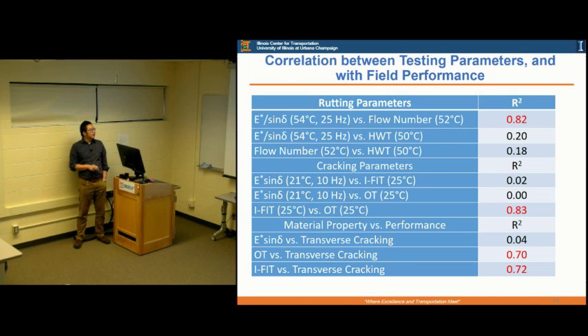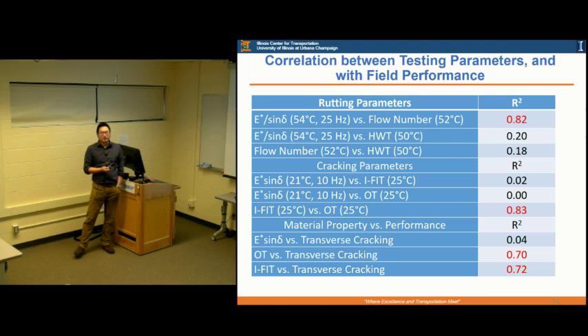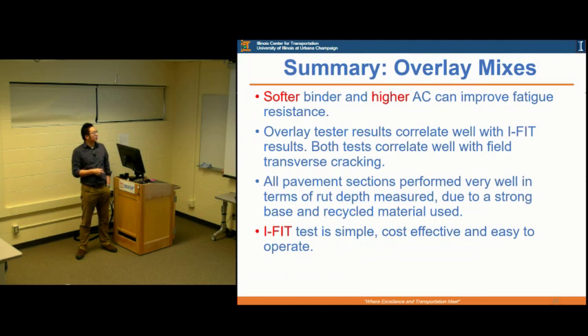So they won't see a very good correlation there. But if we compare material property with field performance, which is the cracking, you see that the overlay tester had a good correlation with transverse cracking, and the iFit is a little bit better than the overlay tester, at 0.72.